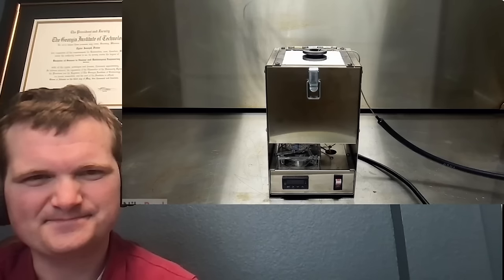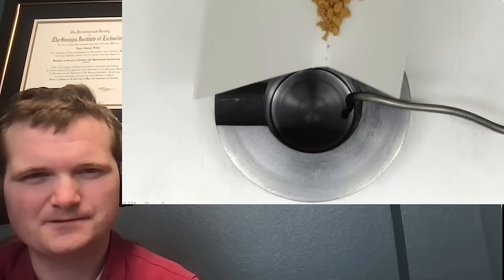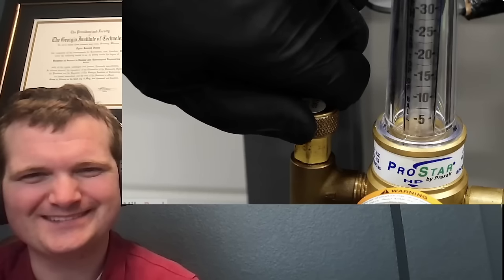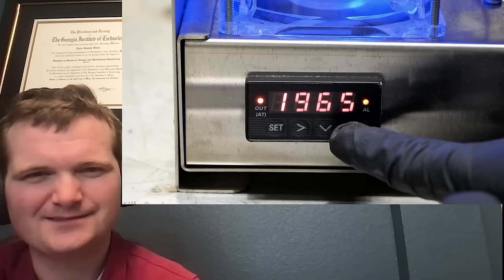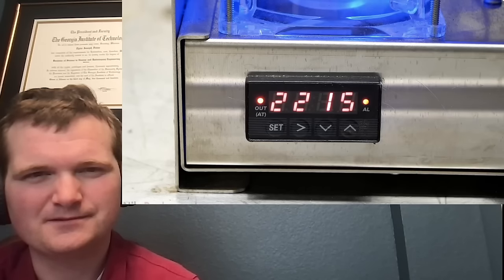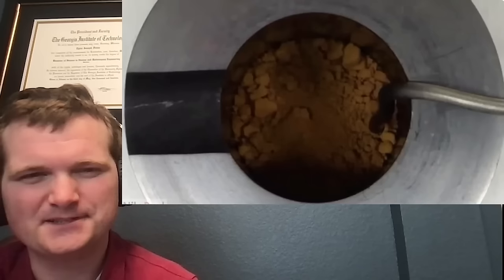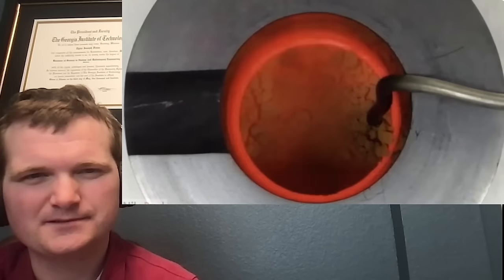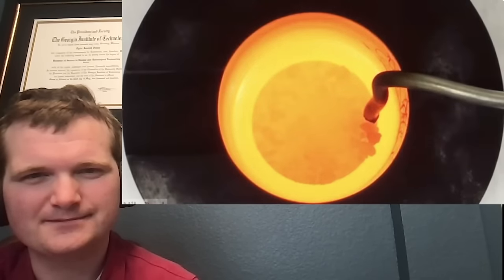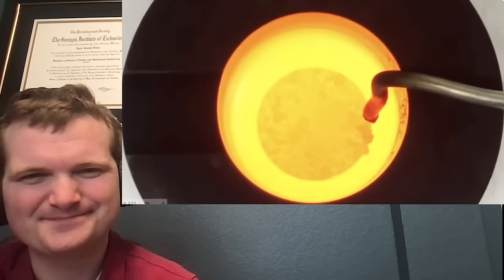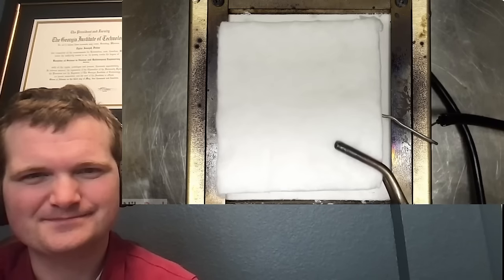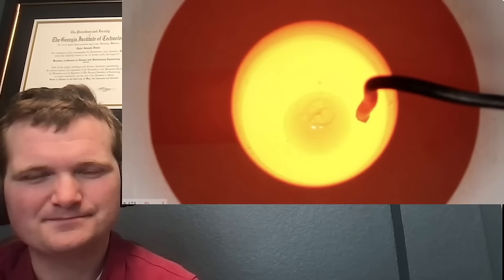What I had now was just a regular furnace with the ability to shoot some argon into it, and I really felt that it was going to work. There was only one way to find out, though, so I quickly added the gold, started a steady flow of argon, and I set the furnace to 2200 Fahrenheit, which is about 1200 Celsius. Over the next 15 minutes, it then slowly heated up, and the gold powder slowly shrank, except it was having trouble melting with the top open, so I covered it with some Kaowool. After that, it only took a few minutes to have a nice little blob of gold at the bottom, and now I could add the aluminum.